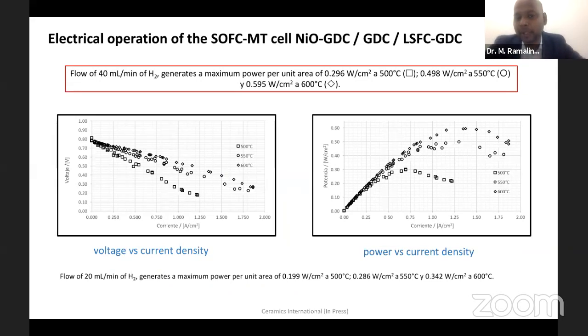In this case, as I told you in the beginning, our aim is to decrease the operating temperature and increase the efficiency. Approximately 0.6 watt per centimeter square is what we generated, say 600. Before that, during the pandemic situation, we worked on developing this. Then we went to nearly 1 watt per centimeter square, and we developed stacks, where each cell is stacked in different modes that I will explain.